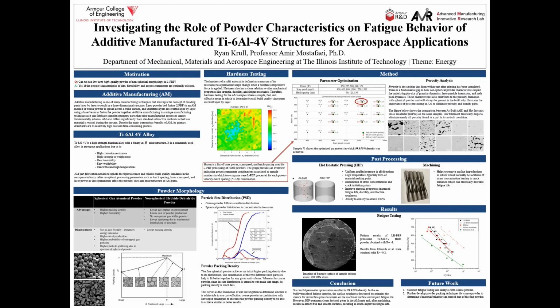In additive manufacturing process, key parameters influence the end result of a build. The parameters focused on in this effort are three main ones, being power, scan speed, and hatch spacing. We investigated various combinations of these parameters and ultimately found an optimal combination that resulted in 99.935% density. Density is important in manufacturing in general, but especially in AM because of shrinkage. For example, if a part is only 50% dense, then upon post-processing, which densifies the part by closing internal pores, the final dimension of the part itself is reduced. Higher dense parts means more reliable parts, which have less defects and less post-processing is needed. In aerospace especially, tight tolerances are of essential importance, and having a large amount of shrinkage is not ideal and results in high likelihood of off dimensions.